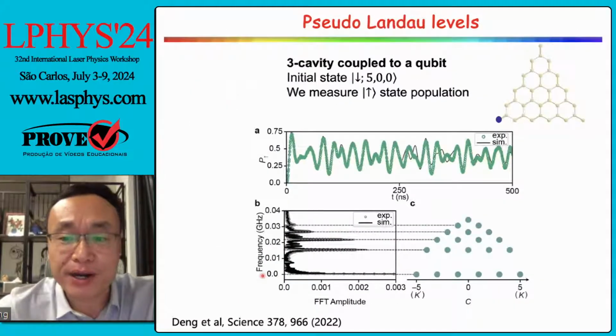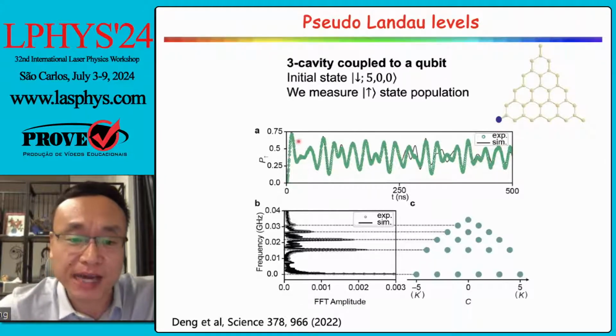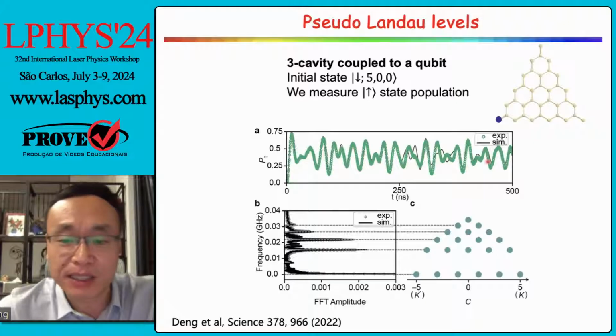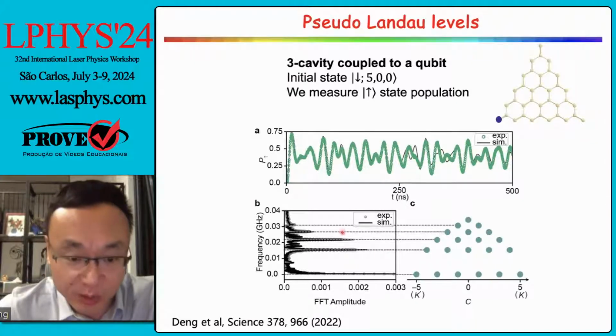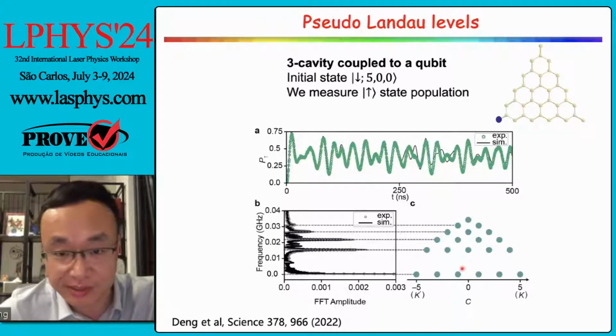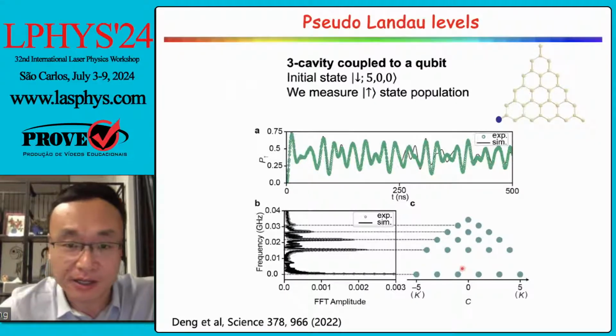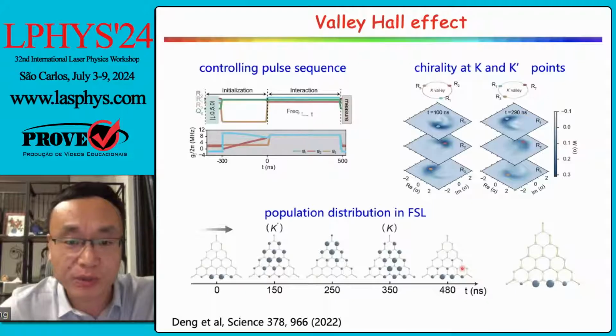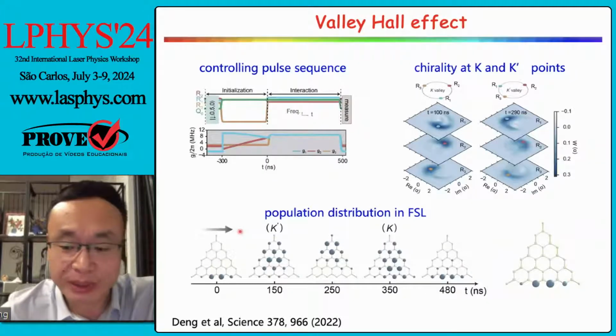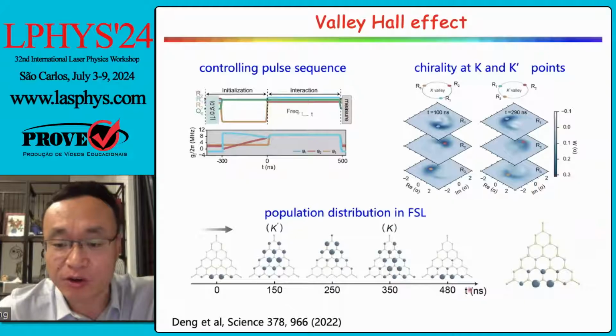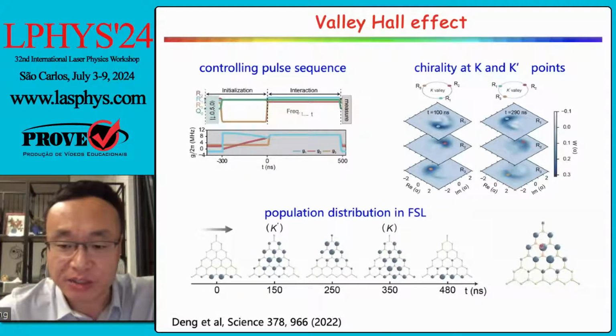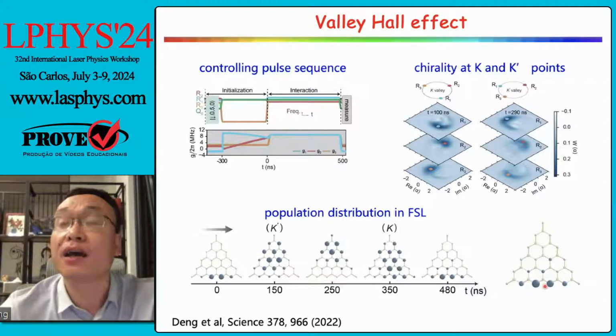And by preparing an initial state on one lattice site and measuring the Rabi oscillation of the atom, we can find this very complicated Rabi oscillation, and then we take the Fourier transform. We find this quantized energy spectra. And these have square root of n scaling. So this is the effective pseudo-Landau level. And we can also introduce the effective electric field and observe this valley Hall effect. The wave function propagates perpendicular to the applied electric field and it goes back.